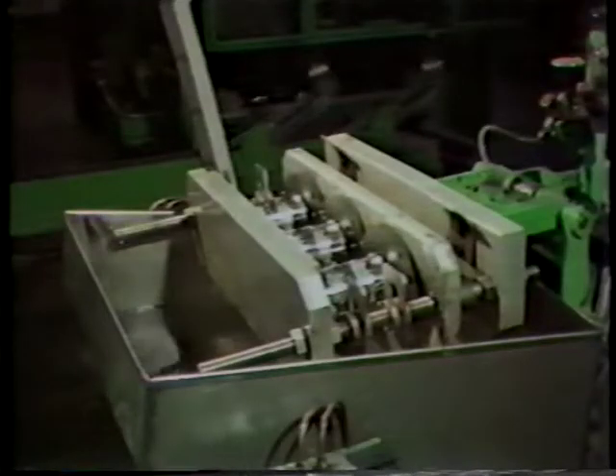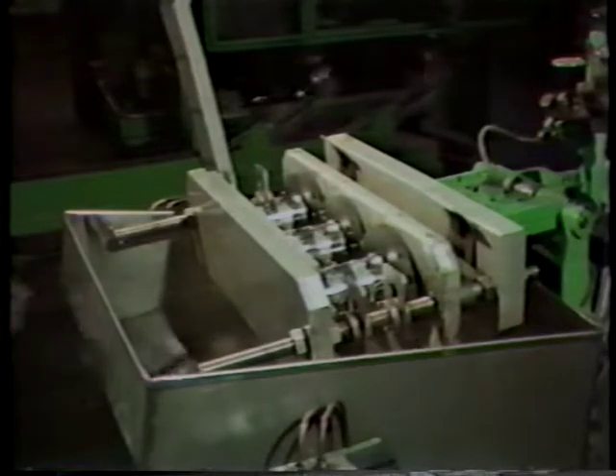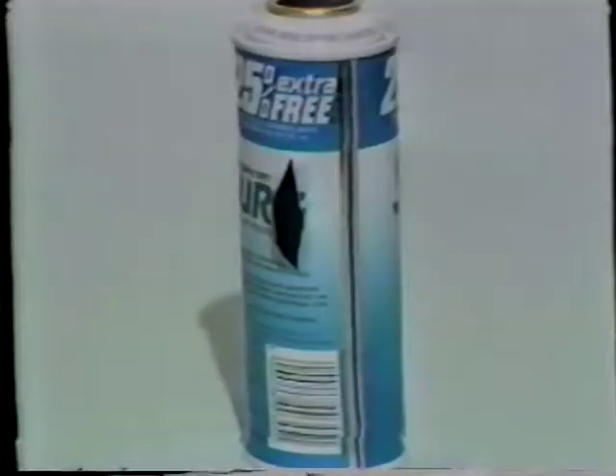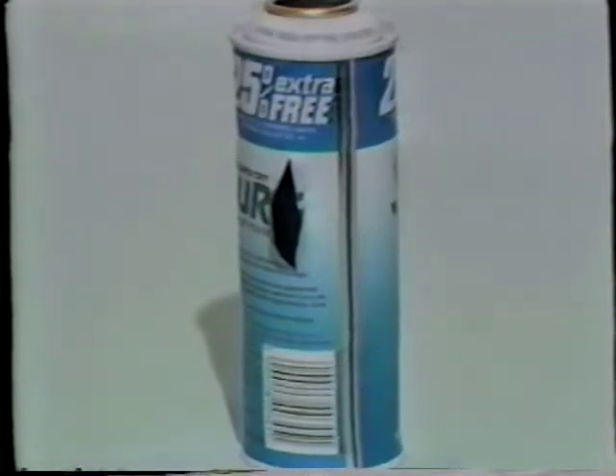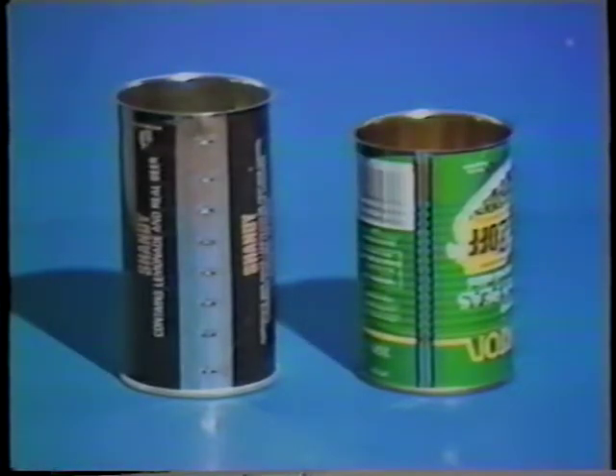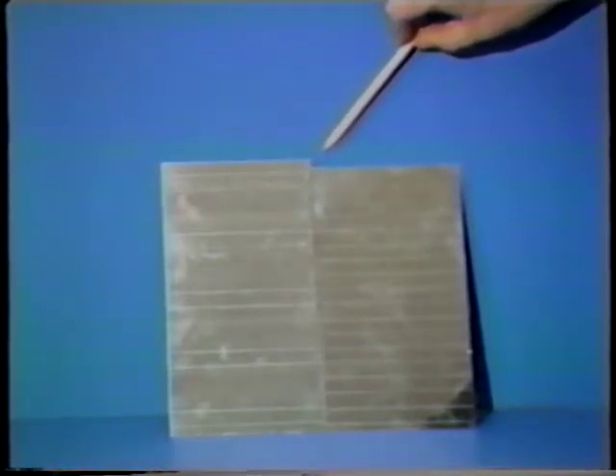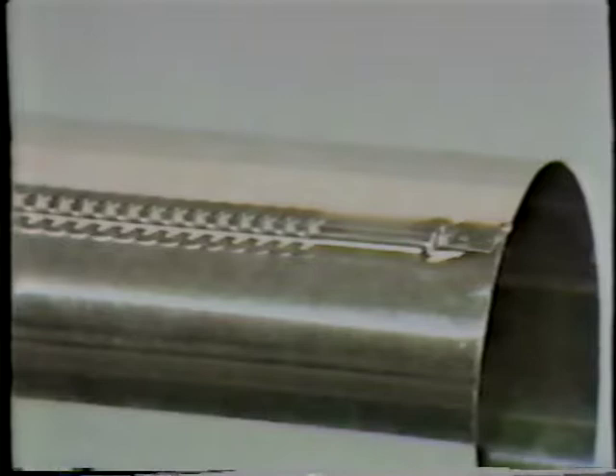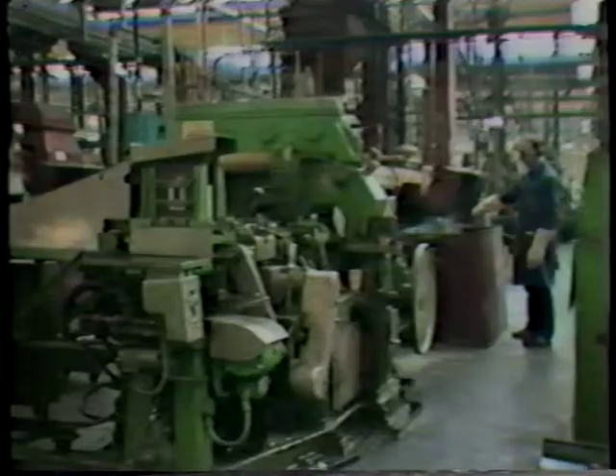When compared with the soldered seam, the welded seam has many advantages. It has a much stronger bond, being able to withstand internal pressures of up to 300 pounds per square inch. The body of the can will split before the weld. The welded seam needs only a narrow margin, giving much more decoration area and a more pleasing appearance to the can. There is a considerable saving in material on the blank size compared to the soldered can. There is only 0.5 mm overlap compared with 5 mm needed for hooks necessary for the lock seams on soldered cans. Just compare the difference between a soldered line and a welded line.